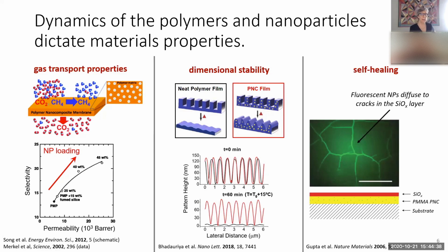And finally, in the case of self-healing, it might be a little hard to see, but down below here, this yellow domain is actually a nanocomposite, and it's coated with silica. And there's a variety of different devices where you're going to have this sort of structure, but the silica can be delicate. And so the composite below, if there's enough mobility of the nanoparticles, can bloom and coat the cracks, in a way making that self-healing, right? That the silica will migrate to those cracks, if the dynamics are right.